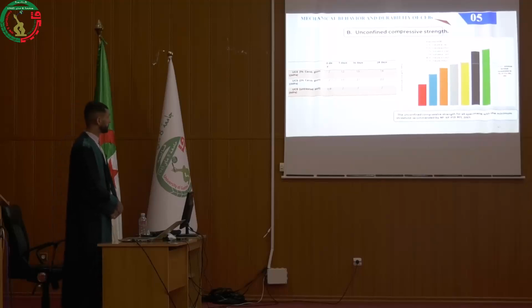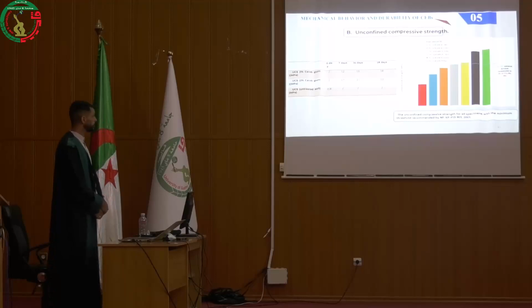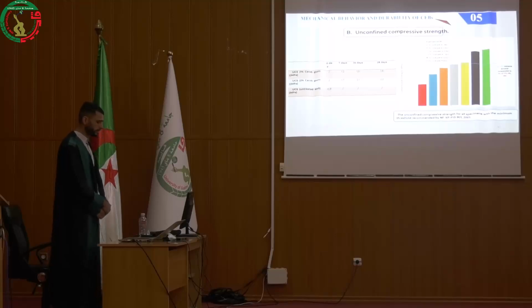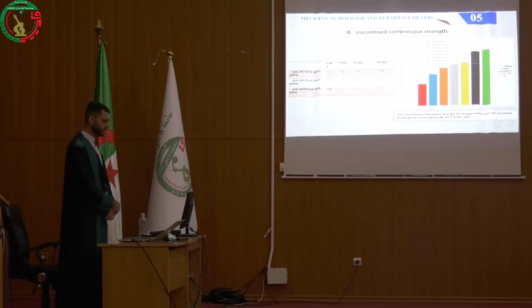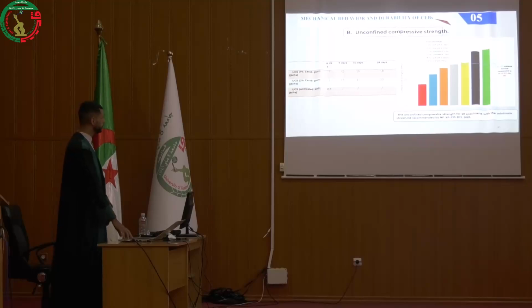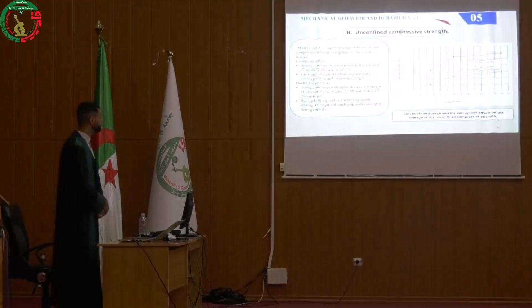The image on the right represents the unconfined compressive strength for all the specimens with the minimum threshold recommended by the French norm. We observed that the unconfined compressive strength of the untreated sample and the 1% carob gum treated sample at 7 days and 14 days fell below the minimum threshold of 1.6 MPa recommended by the CEB standard. However, at 28 days of curing, the unconfined compressive strength of the 1% carob gum treated sample and the 2% carob gum treated sample exceeded the threshold, demonstrating suitability for construction purposes according to the CEB norms.